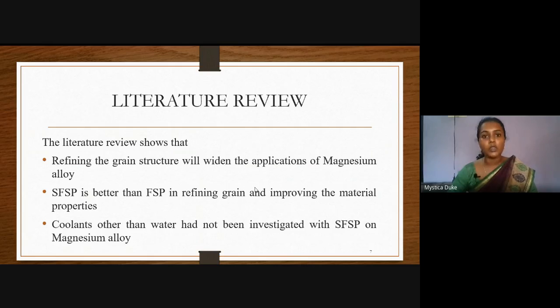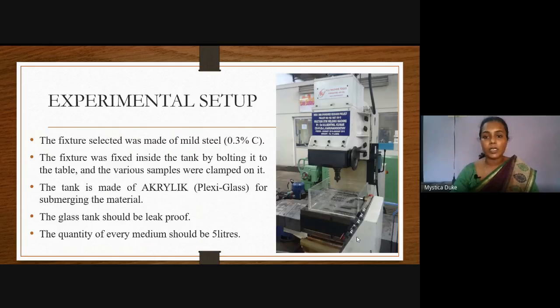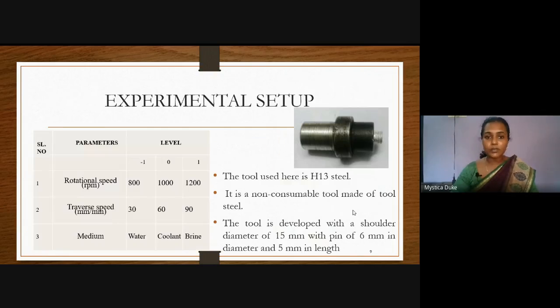Here we have used water to compare, and we have used brine solution and cooling oil. So this is the experimental setup of our study. Here you can see the FSP machine, and this is the tank which is made of plexiglass. The tank is leak proof, and we have used 5 liters of medium for all 3 mediums. And this is the tool we have used. The tool here is H13 steel, a non-consumable tool. The shoulder diameter and the dimensions of the tool are mentioned here.